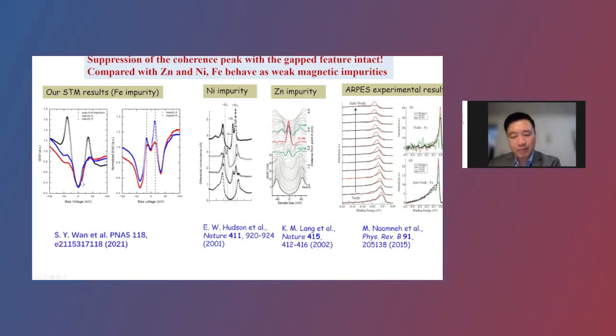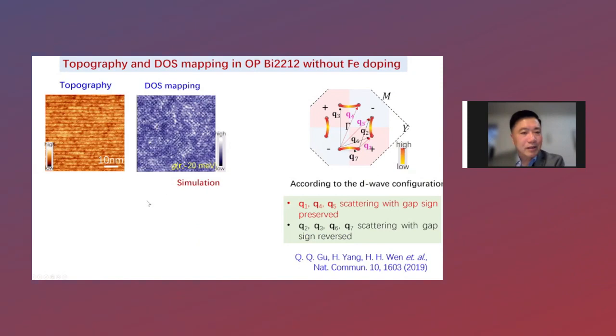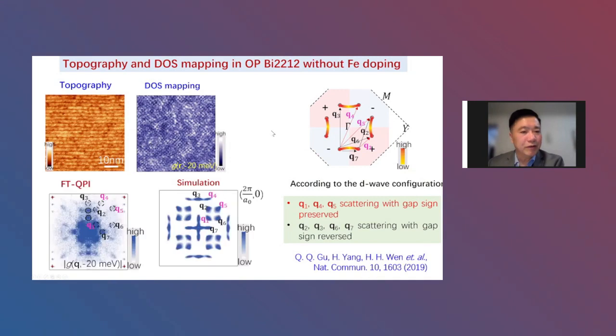Okay, and before going to the spin polarized data on this sample, here I show you that on this BSCCO 2212 optimally doped sample, we know that it has such a kind of Fermi surface. We have seven scattering spots. Okay, and according to the d-wave gap, we have three scatterings with the same sign of the gap, four scatterings with the opposite sign.